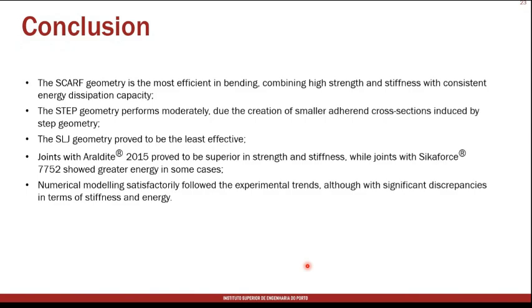Between joint geometries, the scarf one is the best to have a good strength in bending, because it combines the strength and stiffness with a coherent energy dissipation. The step geometry performs worse because of having a smaller cross section at the region of the single step, but the least effective was the single lap joint, which is related to a high offset between the adherends, non-collinearity of load, which leads to the worst result.